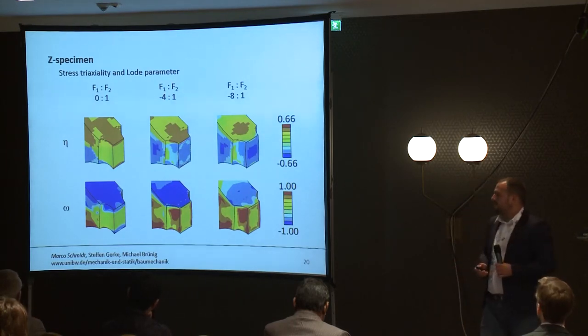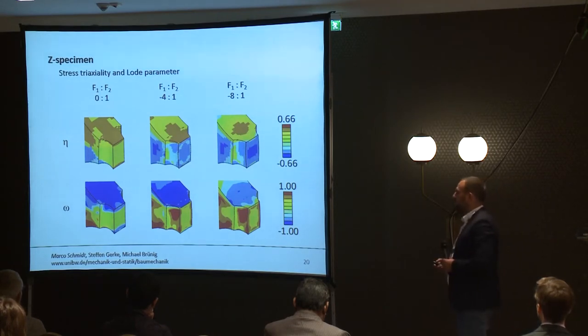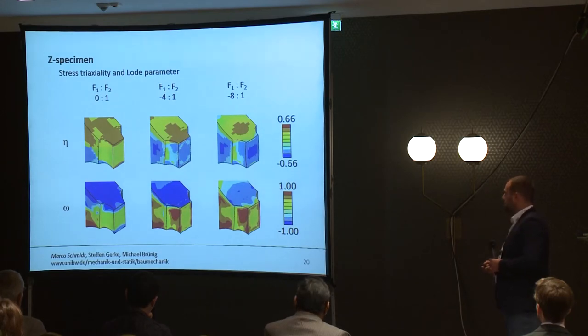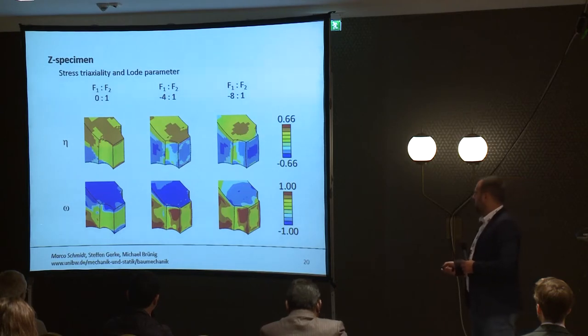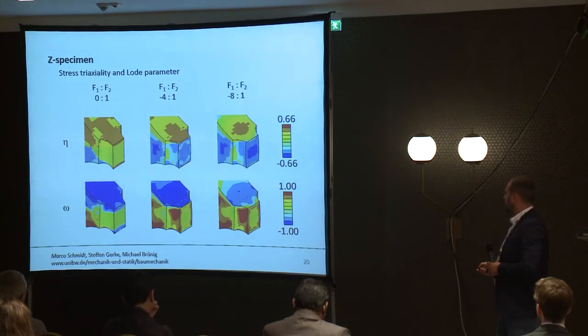Here is the evaluation of the stress triaxiality and Lode parameter of the numerical simulations with special attention to the fracture surface. In the pure shear test, the stress triaxiality and Lode parameter are in a slightly positive range and the distribution is very homogeneous. As the compression increases, the distribution becomes less homogeneous and the stress triaxiality becomes altogether more negative with the minimum lying in the center. The Lode parameter remains slightly positive in the center but becomes much larger towards the edge.